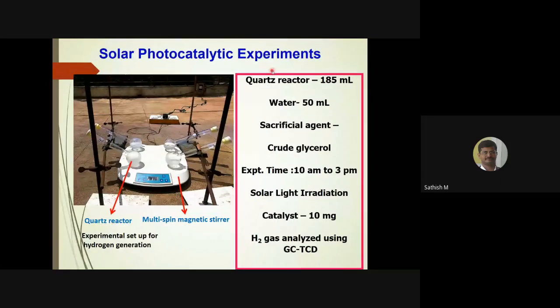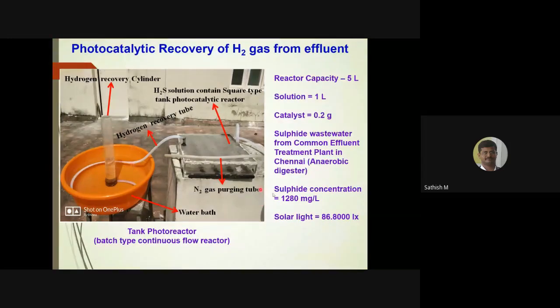So this is one of the solar photocatalytic experiments which we have carried out on a large scale, where we put 185 ml reactors. Here the point is we use only solar light to produce the hydrogen. We were able to produce a larger amount of hydrogen, some millimoles. That means you could really see the bubbles coming out in the system. Simply by a water displacement reaction, you could calculate how much hydrogen you were able to produce. In all these cases, we produce the hydrogen in milliliters, 35 ml, 40 ml, all these things.